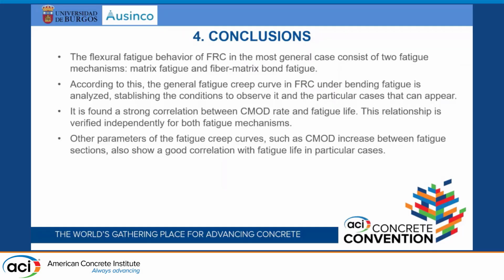And finally, a summary of the main results. The flexural fatigue behavior of FRC in the most general case consists of two mechanisms, matrix fatigue and fiber-matrix bond fatigue. According to this, we have shown the general shape of this curve, establishing the conditions to observe this double curve and also the particular cases that we can see. On the other hand, a really nice correlation has been found between the CMOD rate and the fatigue life. This relationship seems to be independent between the two fatigue mechanisms that act. And finally, there are some other parameters of the fatigue creep curves that can enable us to predict fatigue life.